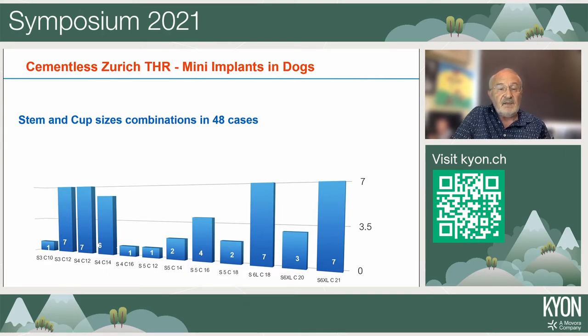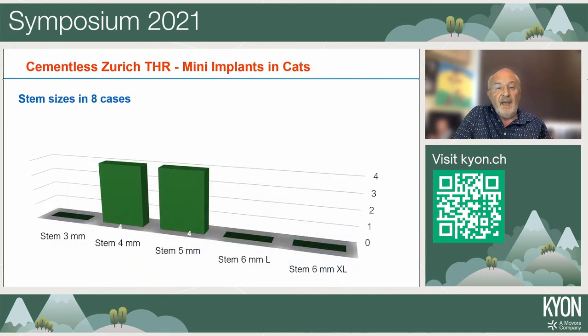It's interesting to see that the most common combinations were the stem 3 with the 12 millimeter cup, or the stem 4 with the 12 millimeter cup, and then going for bigger cases like the stem 5 with the 20 and so on. About cats, the most commonly used are the 4 and 5, but the 4 millimeter we used because at the beginning the 5 millimeter was not available.